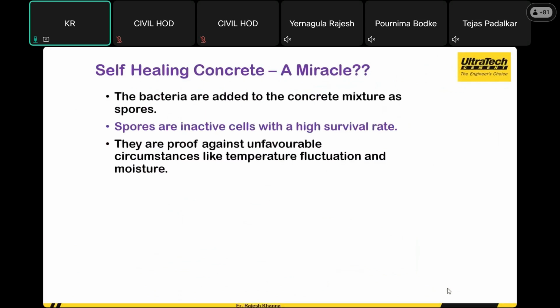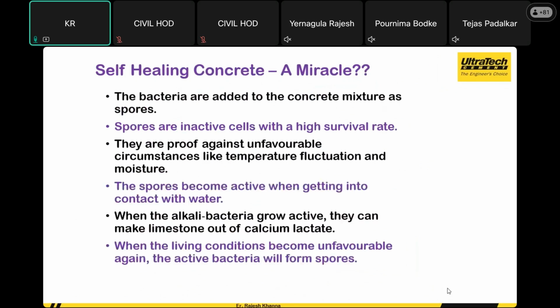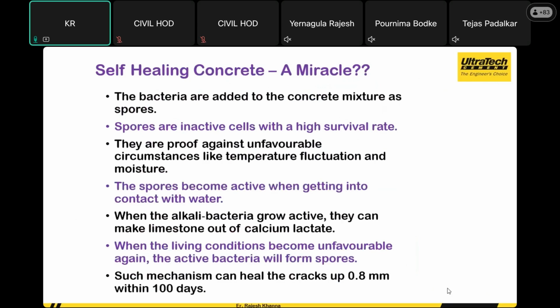It will have a high survival rate, even though any structure will have certain micro cracking beyond 15 years, 20 years also. If there is any presence of humidity or moisture, this will get activated and forms a healing nature. It is just like alkali bacteria growing active, then they make limestone out of calcium lactate and form the healing.